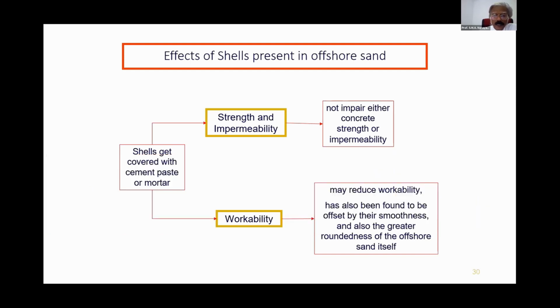So the effects of shell present in offshore sand: the shells get covered with cement paste or mortar in concrete, and that will not impair either concrete strength or impermeability. The workability may get affected because those are flat particle shell fragments, but this has also been found to be offset by their smoothness and also the greater roundness of the offshore sand itself.